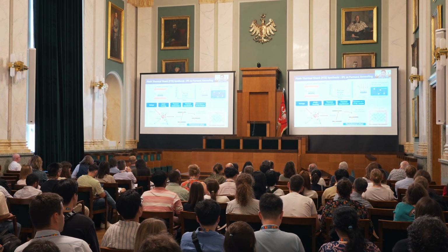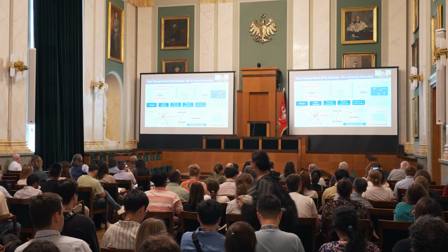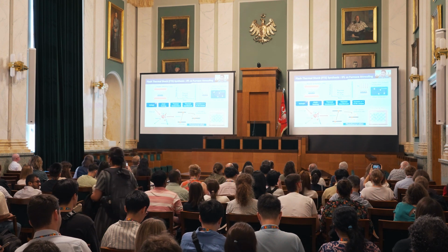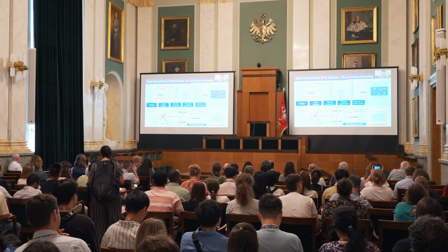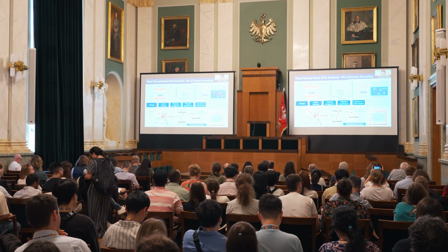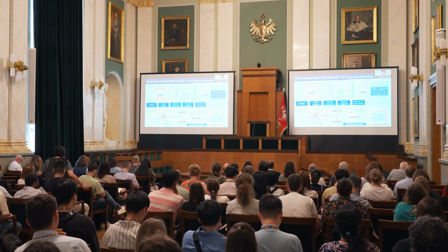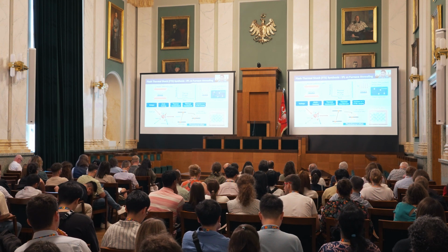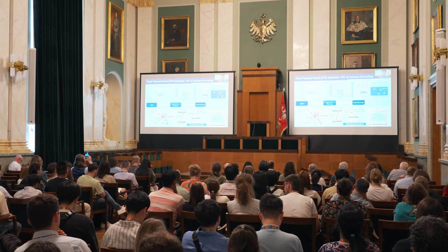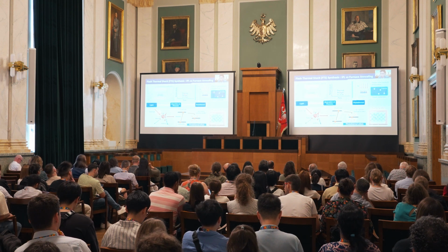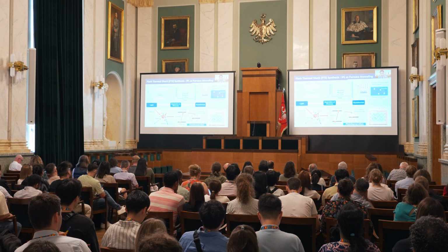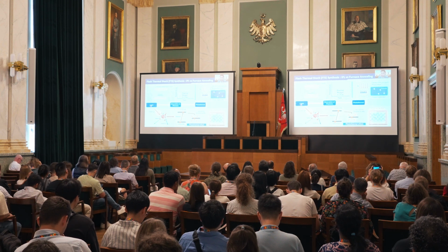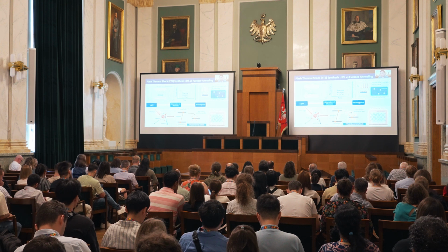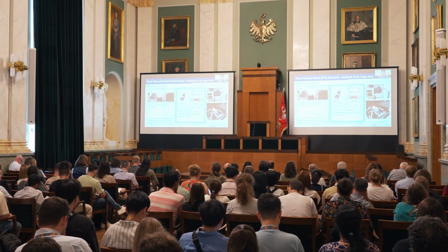In conventional furnace annealing, you can see 5 steps, right? Voltage applied bias, then Joule heating, thermal conduction, thermal equilibrium, then increase in temperature of the sample. On the other hand, with flash thermal shock, the IPL, it is just light exposure, light irradiation, then generation of phonons, then the photothermal effect, and we can see the temperature increase.